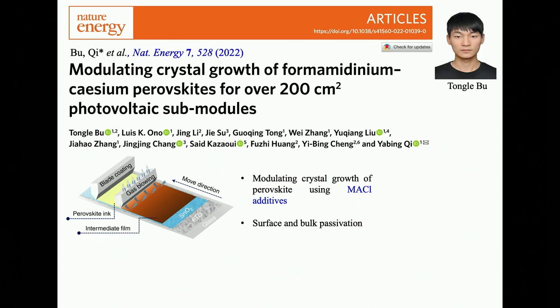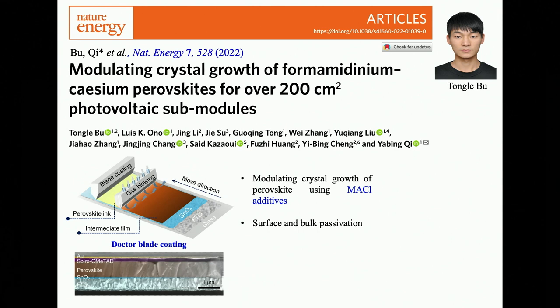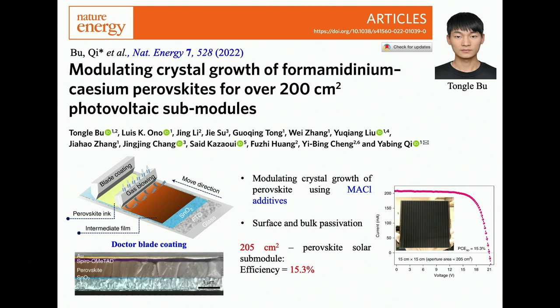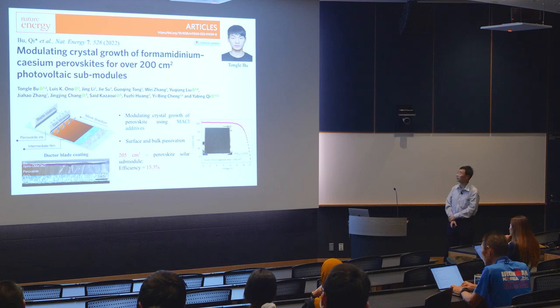In a more recent study, which was performed by Tongle Bu, he introduced MACl as an additive into the perovskite precursor solution to modulate crystal growth of the perovskite thin films. And by combining this strategy with several surface and bulk passivation methods, he was able to obtain high quality perovskite thin film on a much larger scale using doctor blade coating, which is a scalable fabrication method. As a result, we were able to obtain a perovskite solar submodule with area exceeding 200 centimeter square, with an efficiency of 15.3%.